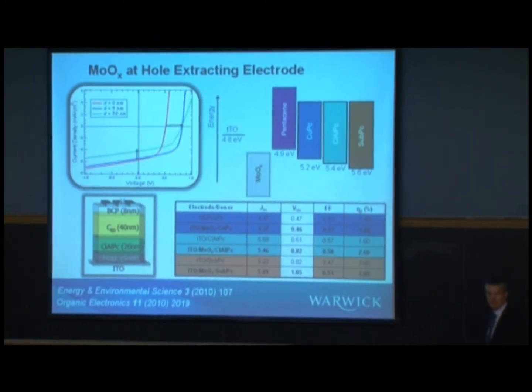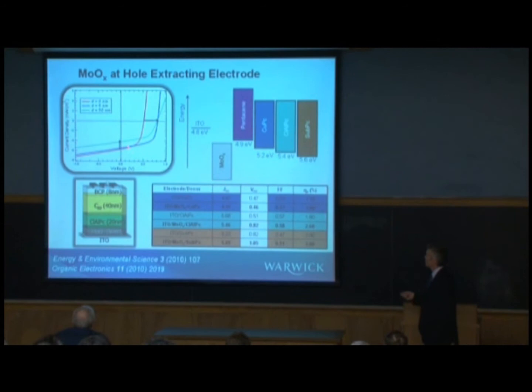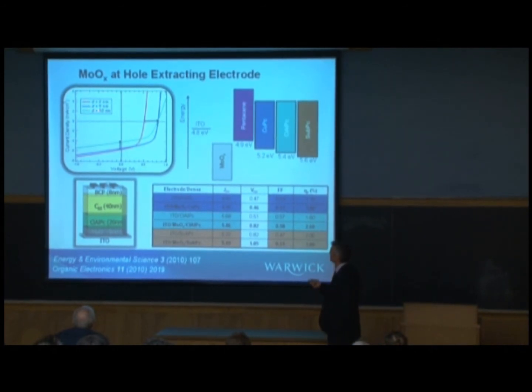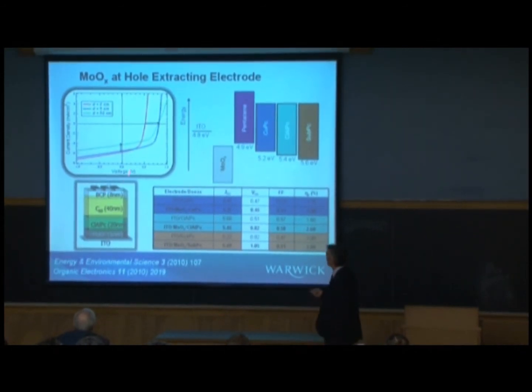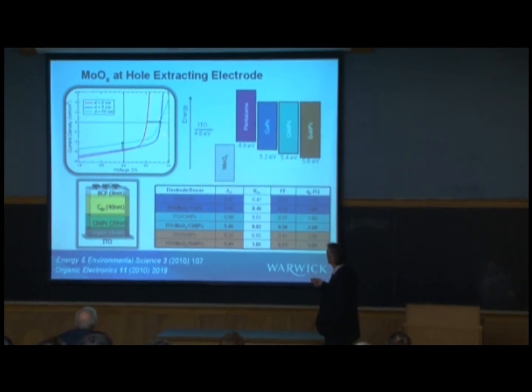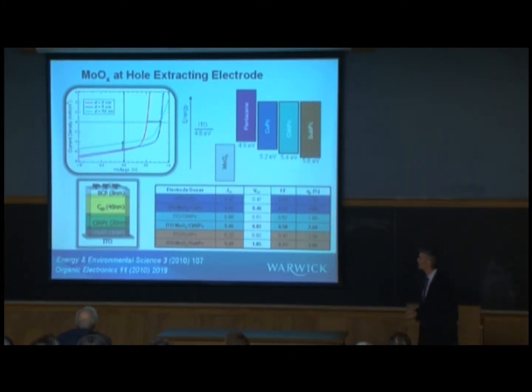In the case of the chloroaluminium phthalocyanine device, if we put down a thin layer, 5 nanometers of molybdenum oxide, then the voltage goes up very significantly to around about 0.8 volts. The current remains essentially the same.